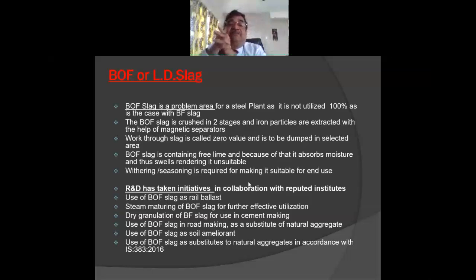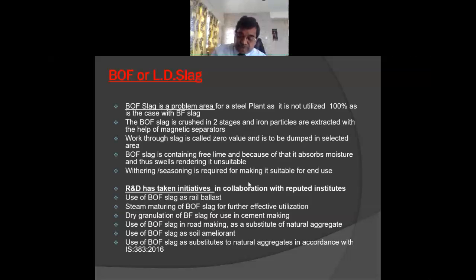And BOF slag, which is a problem area, as you will see that we are using only 24.6%. That I'll be dealing into detail, because this is a problem area. And generation is around 6 lakh tons. We recycle around 1.4 lakh tons. We have not found much alternate use for selling it outside, but we have been doing a lot of research work, which I will discuss in detail later on. And total utilization is around 1.42 lakh, which constitutes only 25% approximately utilization of BOF slag, that is the SMS slag or the LD slag.